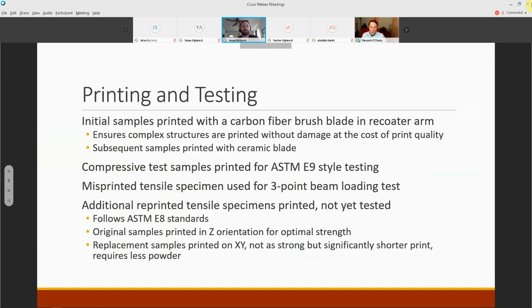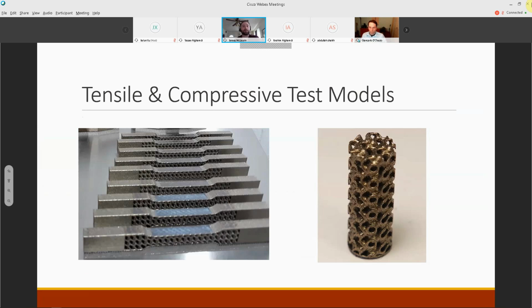We made compressive test samples, an example of ASTM E9. We use misprinted tensile specimen samples for three-point beam loading, and we have also printed more tensile tests for ASTM E8 standards in the XY direction, and we'd like to test those. And I'll pass it off to Waleed.